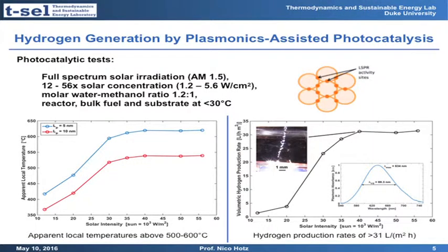A very important result for us, in contrast to what Dr. Glass, for example, said before, is that we see here an exponential increase of gas production rate with concentration, which indicates that it's actually a thermally driven catalytic reaction. There is no electron-driven chemical reaction in this case happening here, in contrast to water splitting systems. And I made it to exactly my time.